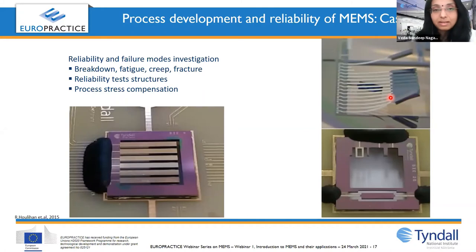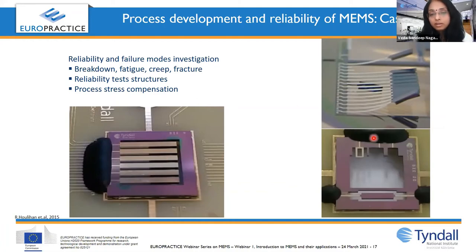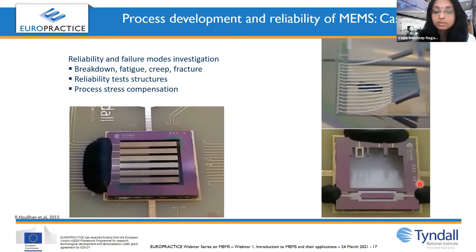For case studies, I would like to acknowledge the Tyndall PiezoMEMS team who shared their fabrication challenges. One challenge involves a cantilever structure: we want a freestanding structure, but during initial runs, due to residual stress, it bends and may even break — showing breakdown, fatigue, creep, or fracture. Reliability testing steps must be put in place, along with process stress compensation mechanisms. Many fabrication iterations are required before getting a good device.